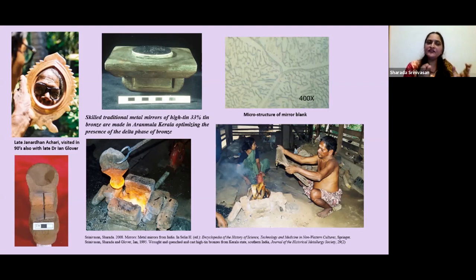So they had actually devised a technique of casting these blanks so as to optimize the presence of this delta phase. A very thin blank was cast by taking two disc molds and leaving a gap within it. And then there's a cup on top where the alloy is placed, and the whole crucible cum mold, as it were, is sealed. When it is heated face down, the alloy gets heated first and then it's tipped over. So it goes in there and fills that cavity. And then you get this very thin blank, which is then mounted on this wooden polishing board. And then it's extensively polished and so on.